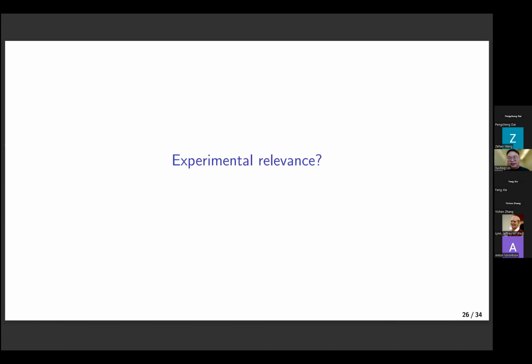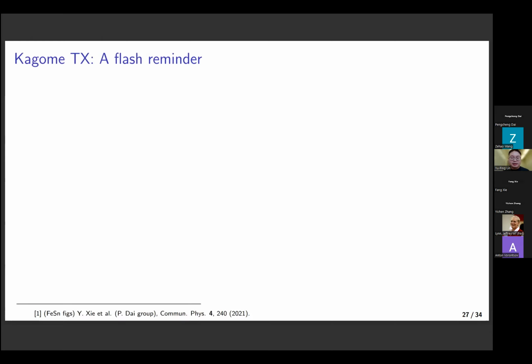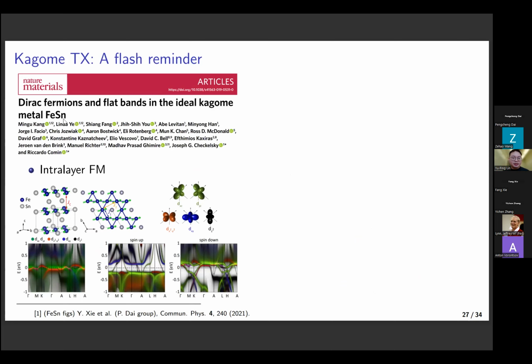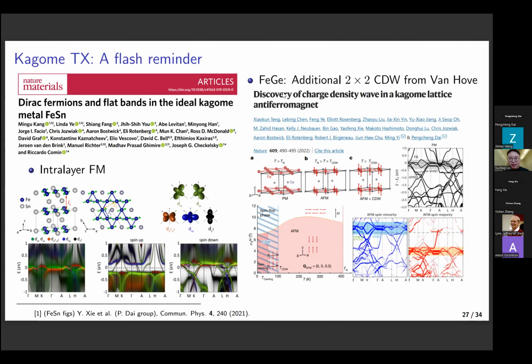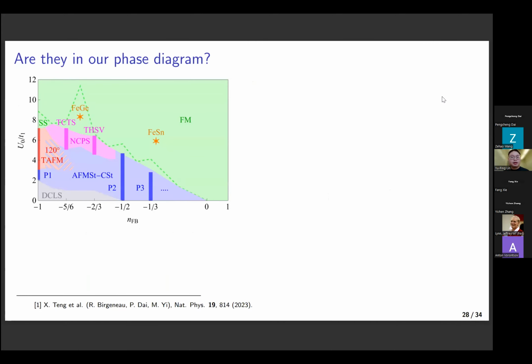So up to now, I've been telling you about our theoretical discovery, but I now want to convince you that our work may also be relevant in the experiments. So let me do a flash reminder of what has been found in the kagome binary materials. In the iron tin, we have intralayer ferromagnetism, and in the iron germanium, there is an additional 2x2 CDW from the Van Hove singularity of the spin minority band. So our important question is, are these materials in our phase diagram?